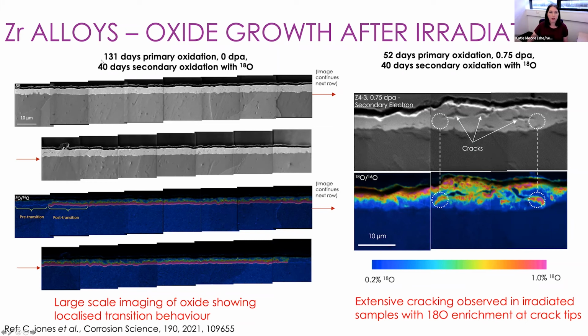So this alloy went through 131 days in an autoclave with normal water, and then it was transferred to another autoclave for 40 days containing oxygen 18. In these ratio maps here, wherever we see pink regions, that's where we have a lot of oxygen 18 incorporation. What this tells us is that the oxygen 18 has penetrated all through this outer oxide and can react strongly with the metal underneath. So we get incorporation of the oxygen 18 at the metal oxide interface.